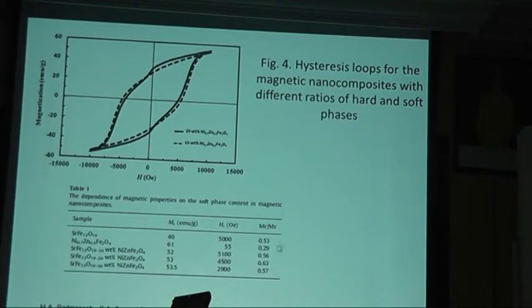So you can see the remnant ratio. I always look at the remnant ratio as one way to check the exchange coupling. If the remnant ratio is over 0.5, I would say that is remnant enhancement. So for single strontium ferrite, the remnant ratio is 0.53. And for single nickel zinc, they get very low, 0.3 remnant ratio, and then they try to play around with the mass ratio of soft ferrites.